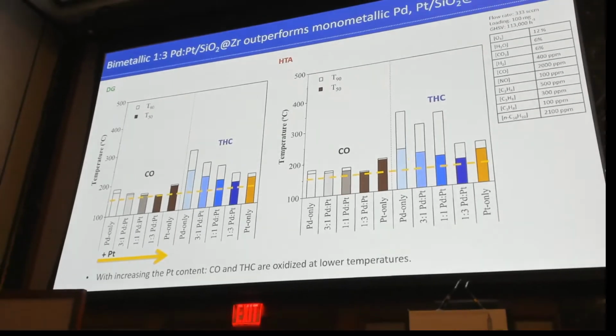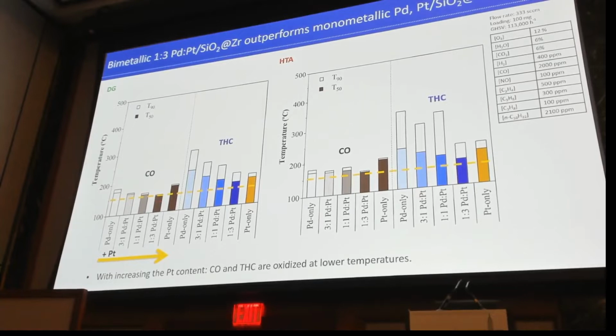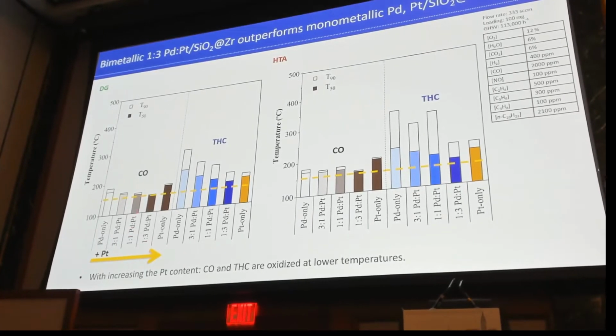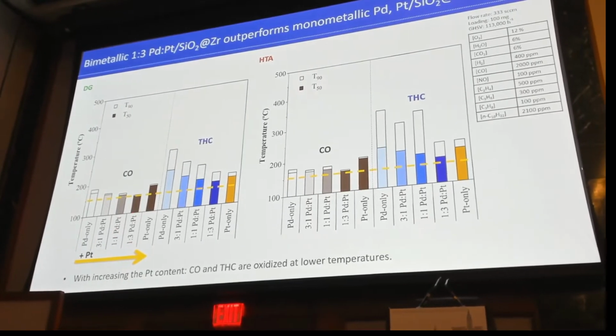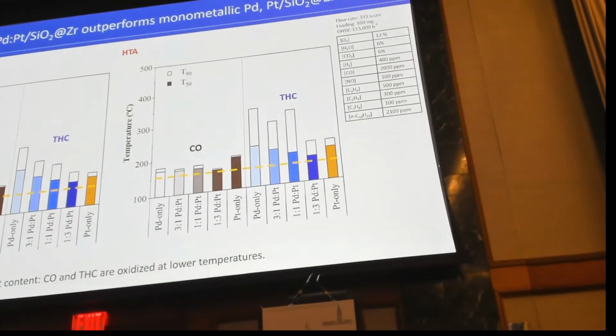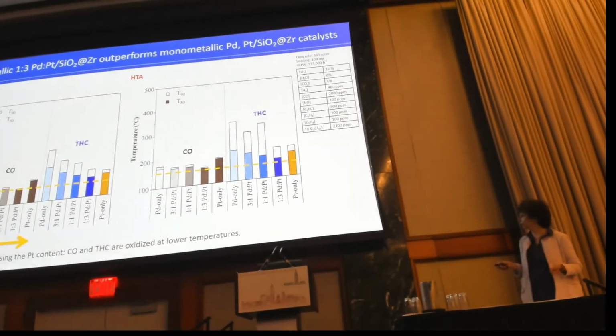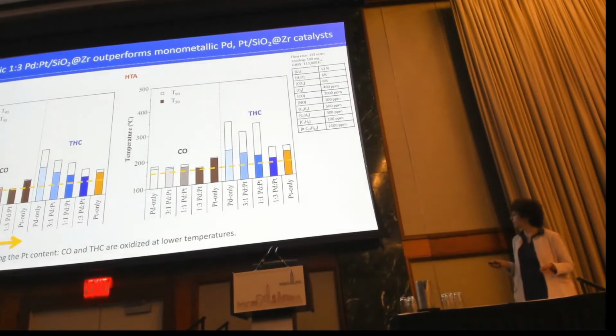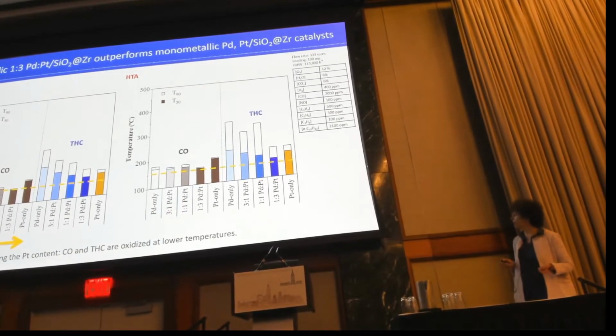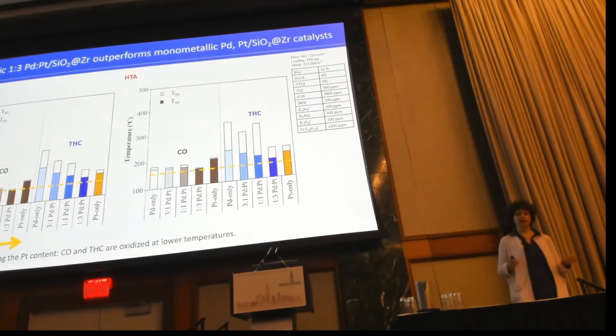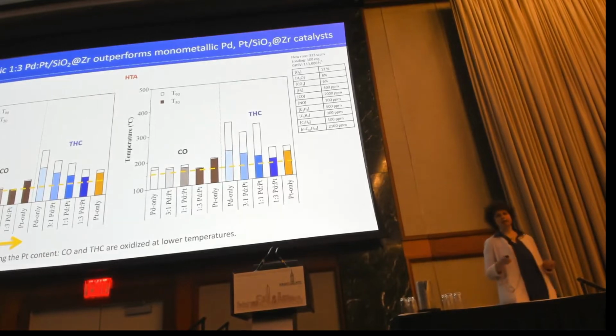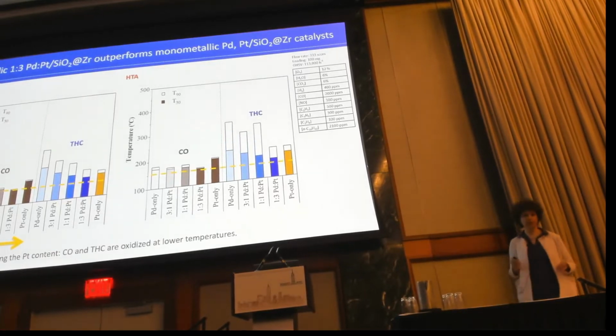So what we see here is that definitely the T50 and T90 decrease, which is a really good thing, that's what we want. And the catalyst that outperforms all the rest is the 1 to 3 palladium to platinum, as I mentioned previously. This is both for green and for hydrothermally aged. So as I said before, we want to understand this catalyst even better, so we start collecting TEM images.